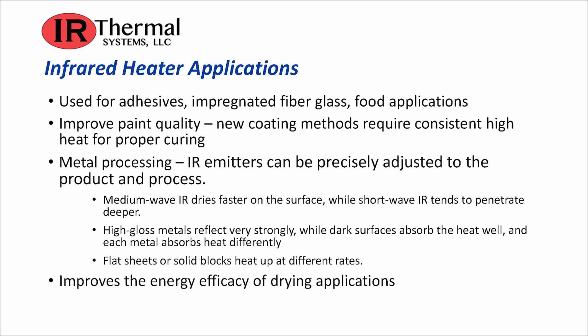Here in the next slide, infrared is also used for adhesives, impregnated fiberglass, and food applications. It's also used to improve paint quality. New coating methods require consistent high heat for proper curing. In metal processing, infrared emitters can be precisely adjusted to the product and process. Medium wave IR dries faster on the surface, while short wave IR tends to penetrate deeper. High gloss metals reflect very strongly, while dark surfaces absorb the heat well, and each metal absorbs heat differently. Flat sheets or solid blocks heat up at different rates. And in general, infrared improves the energy efficiency of drying applications.